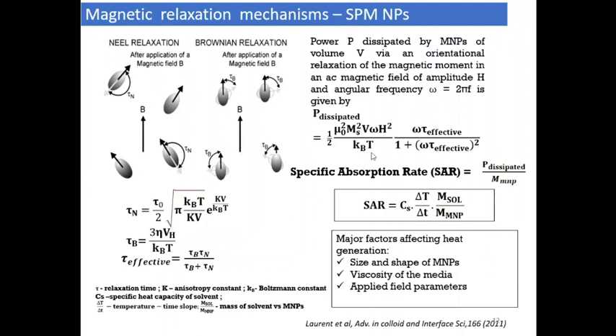So based on this, the specific absorption rate, or SAR value, is equal to the specific heat of this liquid, the water we are taking, times the temperature generation, delta T divided by time. So this is the temperature divided by time. According to the specific absorption rate, the power dissipation divided by the mass of the magnetic nanoparticle will give the specific absorption rate, and that will decide how much temperature is generated. We can measure the temperature in the colloidal suspension.